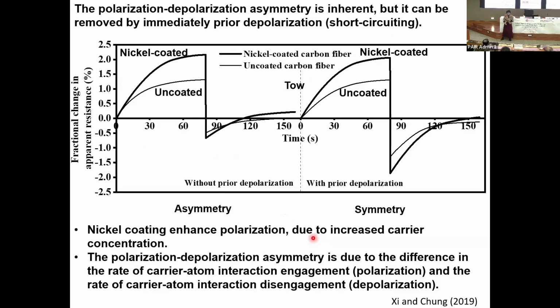Okay. And for carbon fibers, both uncoated and nickel-coated carbon fiber, here is just as is, you see, very asymmetrical. But if you do short-circuiting so as to depolarize it just prior to the electrical measurement, see, it's symmetrical for both the uncoated and nickel-coated carbon fiber. And also note that the curve is higher up for the nickel coating than without. So the nickel coating enhances the polarization due to the increased carrier concentration. Nickel is a metal, carbon is not.